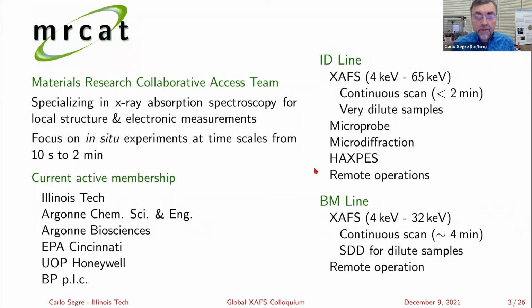We also have a nice Vortex 7-element electrically cooled detector, so we don't have to use liquid nitrogen, and that really works well for dilute samples. We've been getting the electronics up and running, and it's performing quite nicely. We have a microprobe. We can do microdiffraction. We have a high-energy X-ray photoemission system in the back of the hutch, and we've done a lot of remote operations over the last 2 years.